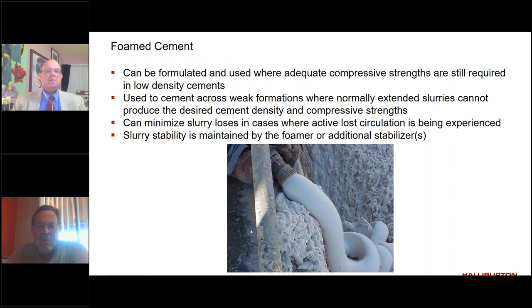Wanted to talk a little bit about foam cement. Foam cement is fairly unique in itself because it tends to be lightweight. We can pump foam cement that is even lighter than water, so it actually floats on water, less than 8.3 pounds per gallon. The way we do this is we take our cement and mix it with water, so now we have that wet slurry. In the slurry, we then have a surfactant, and as we pump the wet cement with the surfactant, we inject nitrogen into it. That nitrogen is injected at a pressure where it actually foams. If you can see the picture on the screen, it looks just like shaving foam.